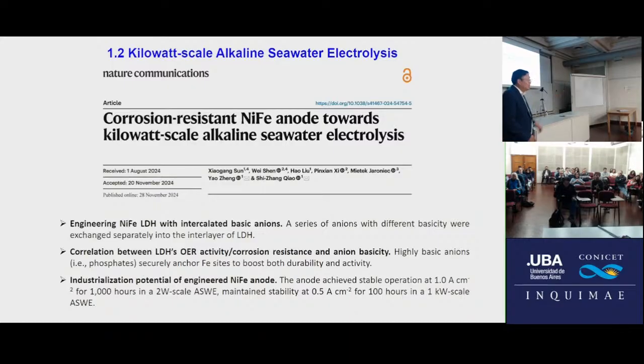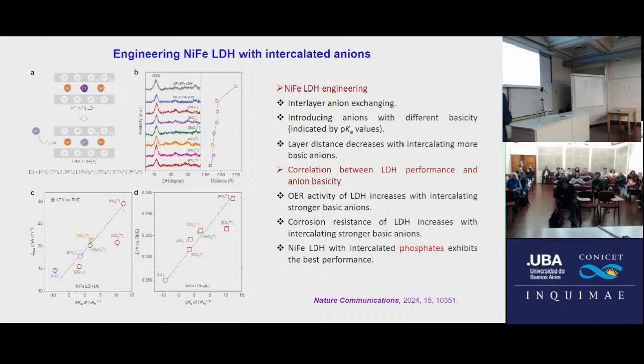Yeah, after that we found which one is the best: phosphate is best. Okay, here are the details. We used 7 different ions. We established a relationship between the activity and the corrosion resistance, with ion basicity. So we found that phosphate is the best modification ion.